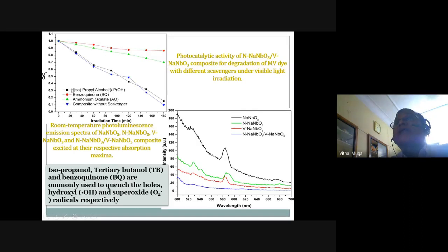Where is the isopropyl alcohol? Now this is the one, the black one. Now the black one, it has not changed. That means holes are not actively participating in the mechanism of the methyl violet degradation. Then what is participating? See, red is benzoquinone. Benzoquinone means superoxide radicals are formed considerably. So in other words, we can find out the mechanism of the dye degradation using this scavenging test.